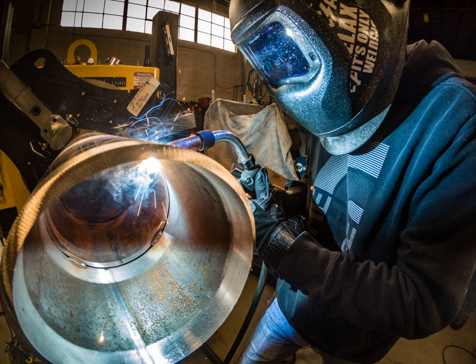The efficiency is dependent on the welding process used, with shielded metal arc welding having a value of 0.75, gas metal arc welding and submerged arc welding, 0.9, and gas tungsten arc welding, 0.8. Methods of alleviating the stresses and brittleness created in the HAZ include stress relieving and tempering.